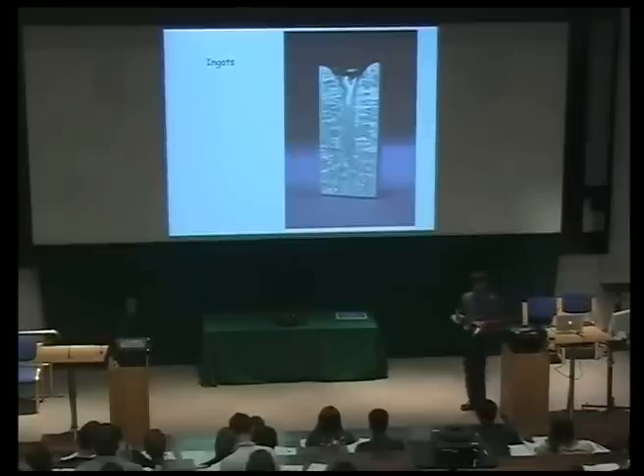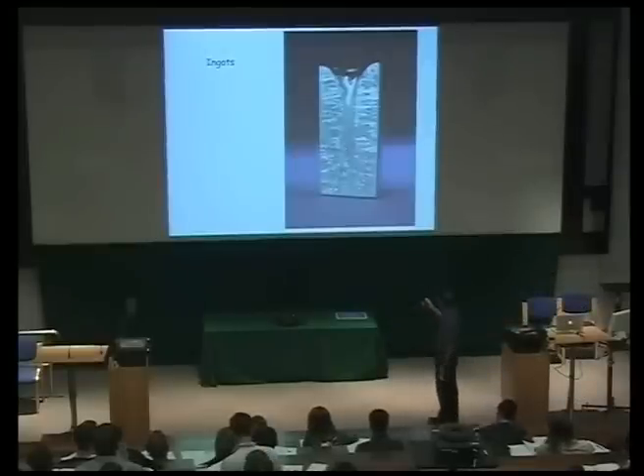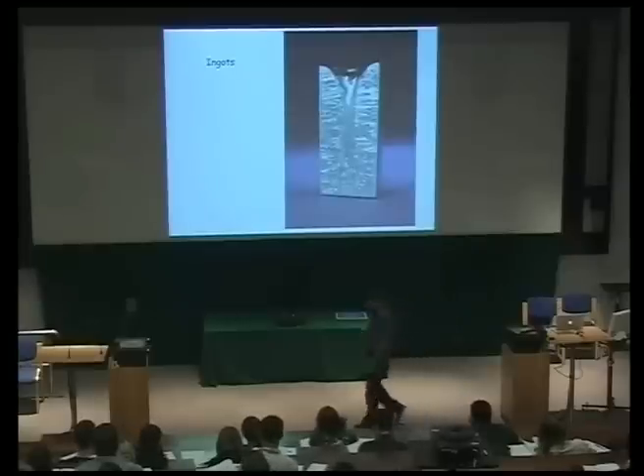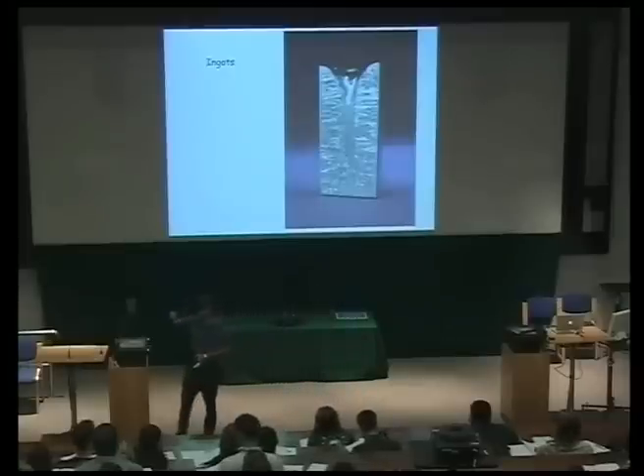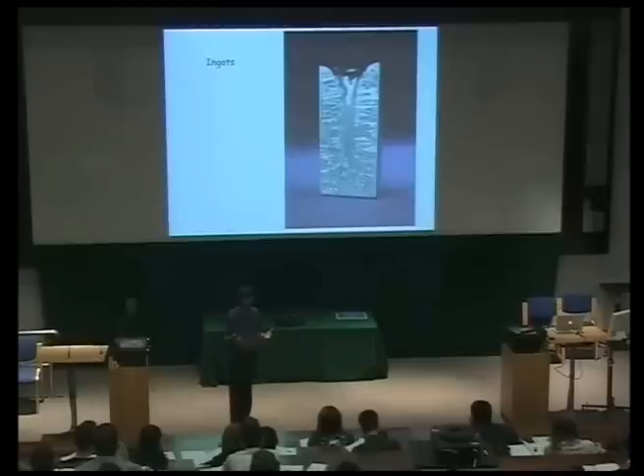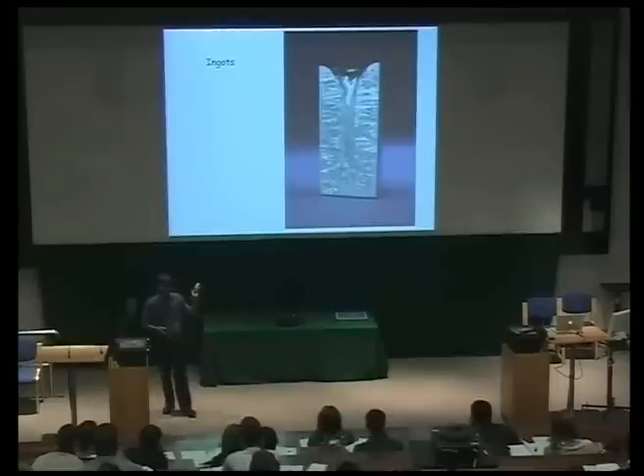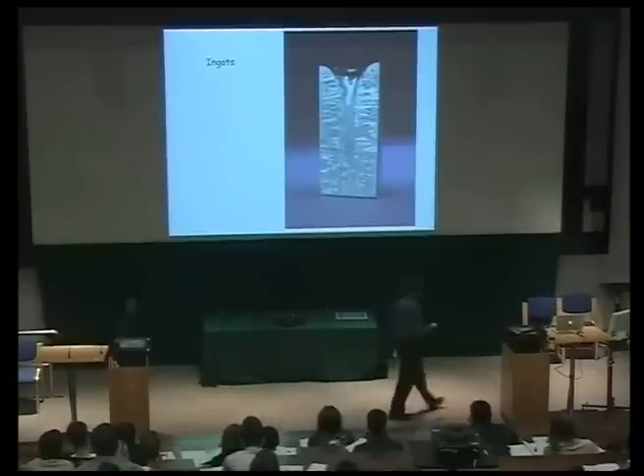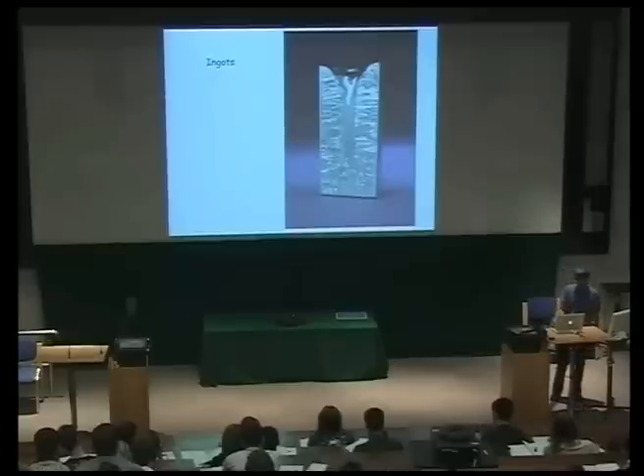You remember this slide showing metal poured into a mold — we have fine crystals here, coarsened because some are stifled off by those growing more rapidly — and you end up with this pipe because the liquid has contracted and there's nothing to feed liquid into that void left by the contraction. Well, this is extremely wasteful — imagine having to throw away that much material. So ingot casting — casting metal into a mold and letting it solidify — is hardly ever used except for making very special small quantities of materials. Instead, you have this fantastic process known as continuous casting, which completely removes this problem and many others.